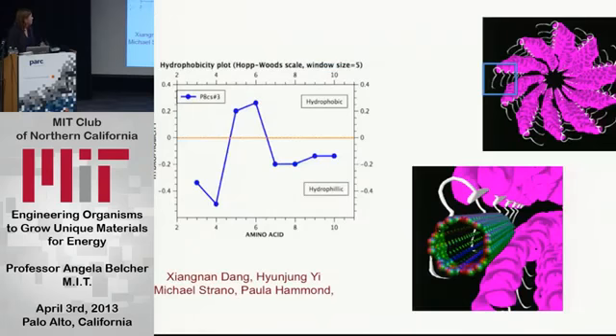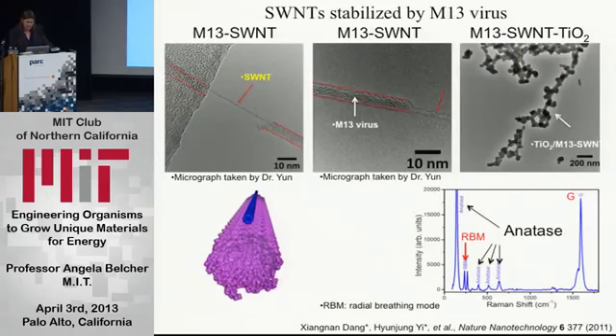And so I'll just skip through this. This is for the biochemist people in the audience, showing you, yes, a virus can be a surfactant, and the sequences that we came up with were surfactant-like sequences. And here's a virus binding a single-wall carbon nanotube. We make lots of carbon nanotubes, and then they actually have a sequence that can grow titania. You grow titania around them, and so now you have a virus with carbon nanotubes and titania over them.